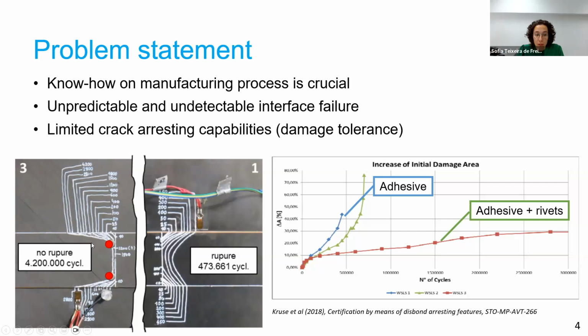While when you have the adhesive plus the fasteners, the crack grows in a much more stable manner. So the rivets can hold and arrest the crack. And this is why in current primary load bearing structures, the certification does not allow to have only bonded joints. It must be a bonded joint with some kind of design feature that can arrest the crack.